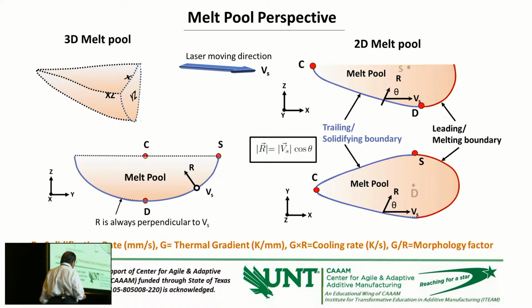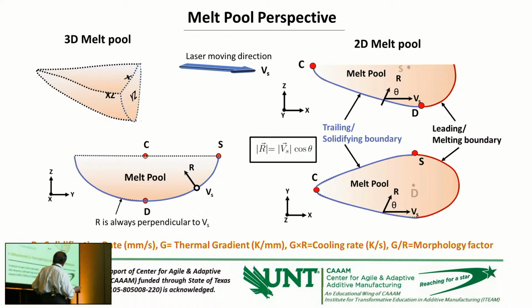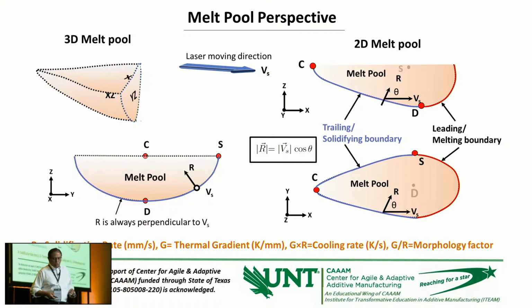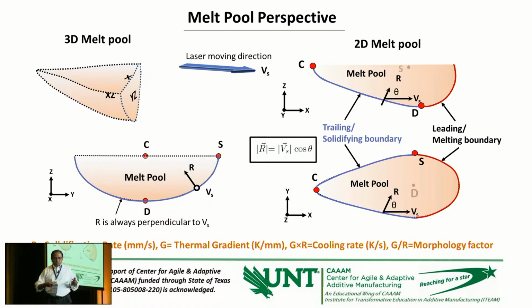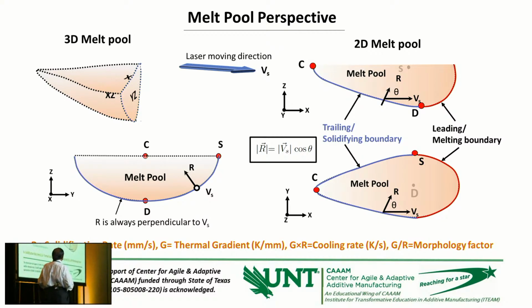Now, one thing I want to show you here, I'm just giving you a broader snapshot. What is important to look for in these model-based predictions? With these models, you can get the solidification rate, the thermal gradient, the cooling rate, and a morphology factor. Solidification rate will control how large or small the grains are in the final structure. Thermal gradient will give you how the grains grow, in what direction they grow, and what crystallographic texture they will produce.